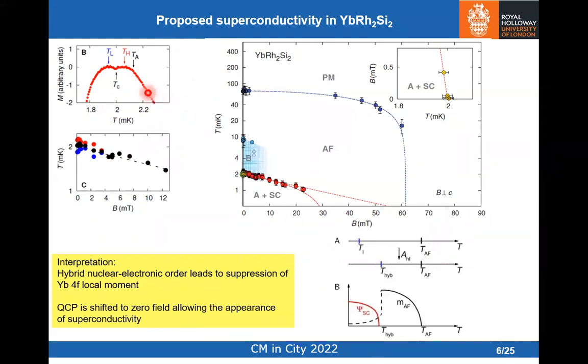Looking at the magnetization data, there's a peak in magnetization around 2 millikelvin, and the paper contains interpretation of these various features around the peak. The locus of that peak as a function of magnetic field is these red points here, and so the interpretation then was that below these temperatures you have both antiferromagnetism and superconductivity. The interpretation offered was that at this temperature you get hybrid nuclear-electronic order, which leads to suppression.